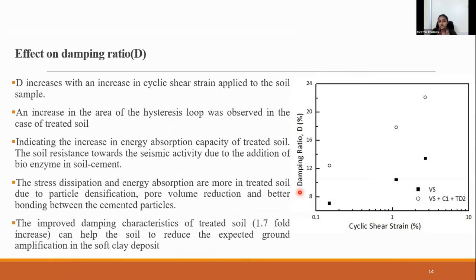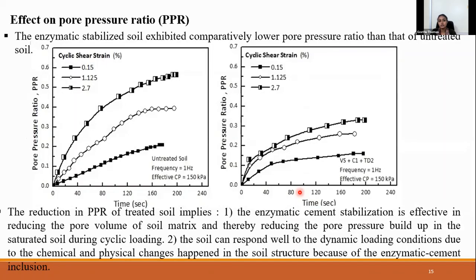That means the stress dissipation and energy absorption is more in the treated soil due to particle densification and pore volume reduction. That means the soil can reduce ground amplification because of the treatment. And also the pore pressure response is studied. You can see the pore pressure ratio got reduced because of the presence of treatment. That means the enzymatic cement stabilization is capable of reducing pore volume and thereby reducing the pore pressure ratio in the saturated soil during cyclic loading.